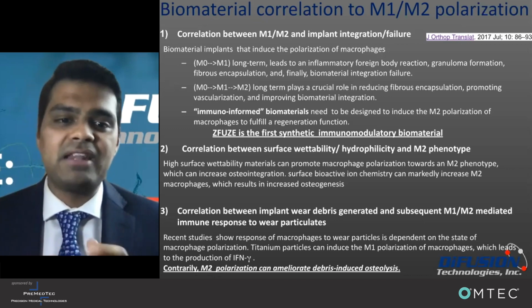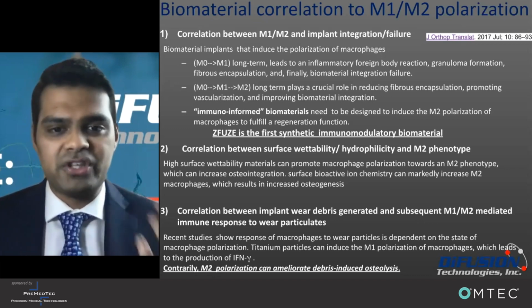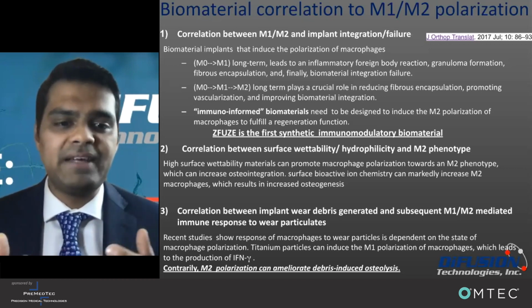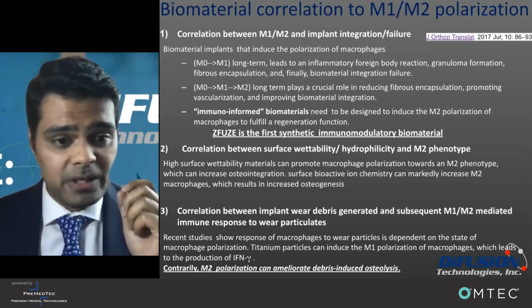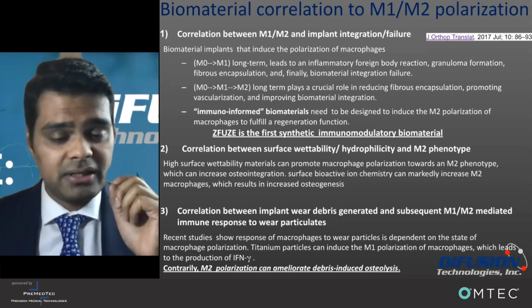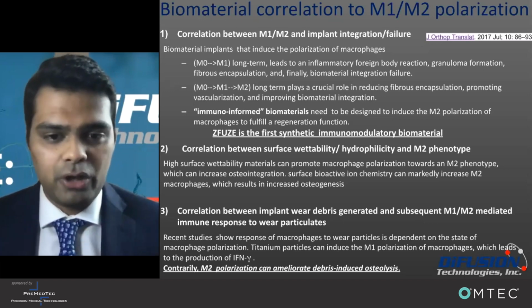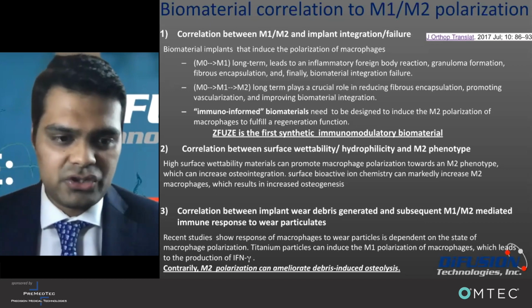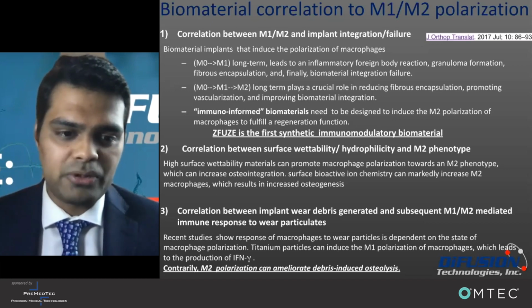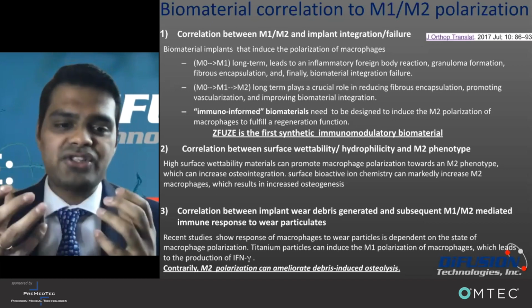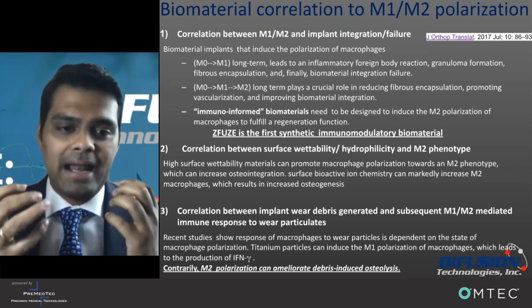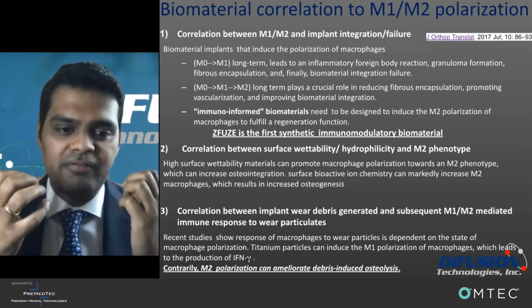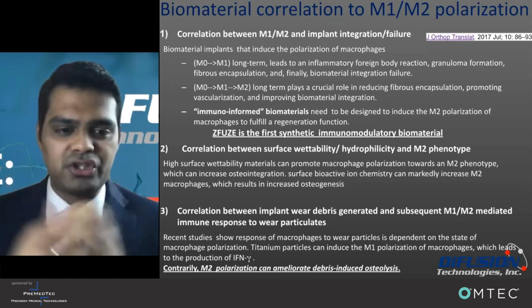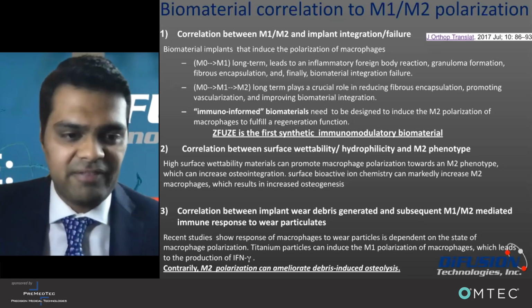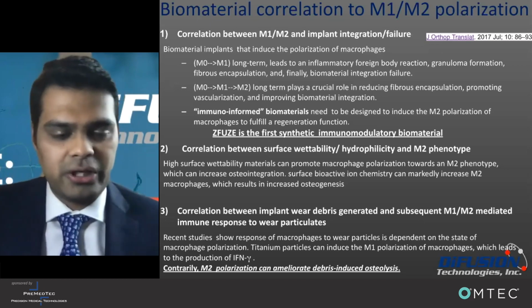And we believe that there's a huge correlation between surface wettability or hydrophilicity and M2 phenotype. And we also believe that implant wear debris, especially from titanium, has resulted in M1-like phenotypes, which have been documented in various scientific papers out there. So understanding this osteoimmunology and actually keeping that as an important factor in tailoring the next generation orthopedic biomaterial is going to be a very key factor in terms of predicting downstream clinical response.